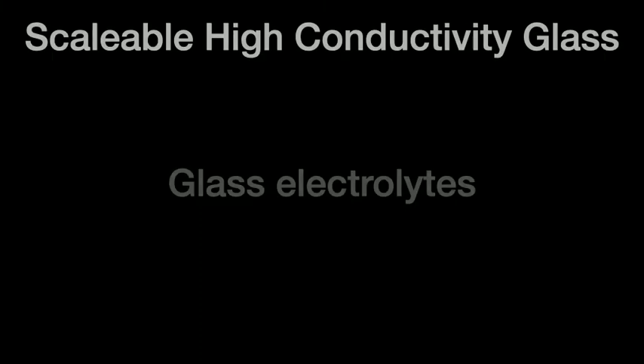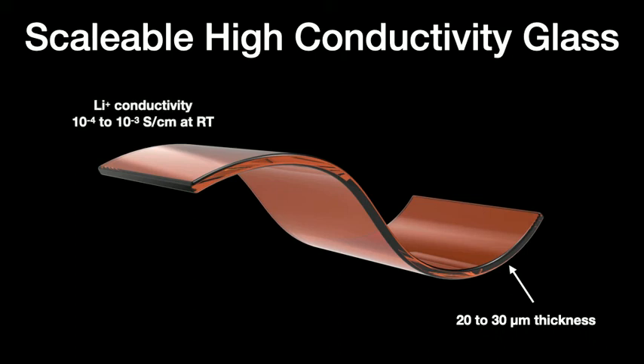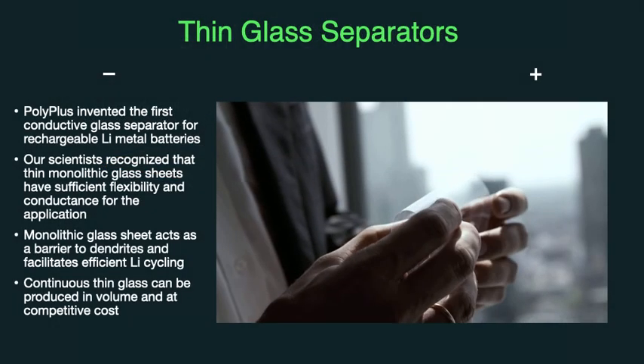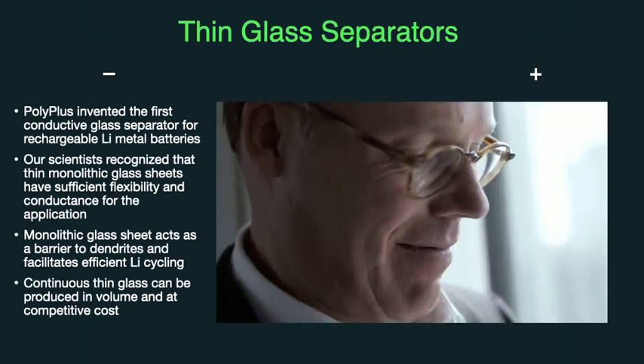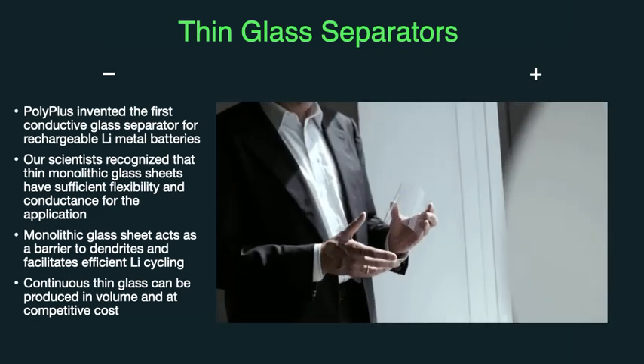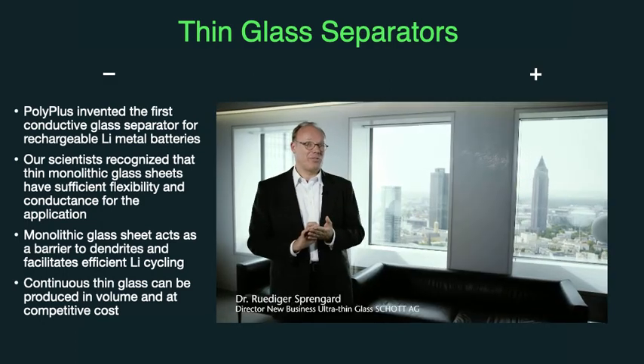So PolyPlus is working in this area, glass electrolytes. The idea is to use high conductivity sulfides, which can be processed through melt processing, high-speed manufacturing techniques that are used to make display materials. The iPhone and smartphones all have a thin glass membrane sitting on top, which is quite inexpensive. Computer displays and large TVs also have thin glass displays. And when you get down to the kind of thicknesses we're talking about, glasses become quite flexible, almost like polymers. You can see here about a 50-micron sheet of glass being handled very much like a piece of plastic.